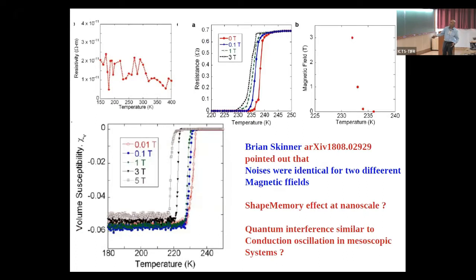So, for example, in one of their papers, the susceptibility dives down, and it's like a Meissner, complete flux expulsion, but there's a lot of noise. And then at the TC, the resistance doesn't become zero, but it's many orders of magnitude less than that of silver or copper. And then resistivity fluctuates like this erratically. And then in a stable situation, if you apply a magnetic field, the TC does go to zero. So the magnetic TC does reduce.